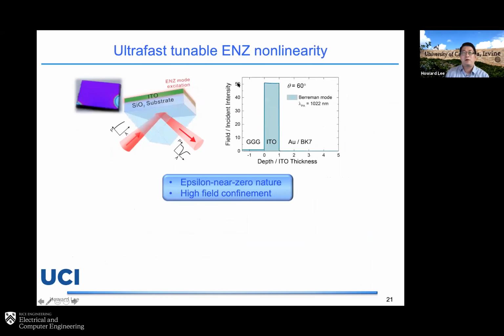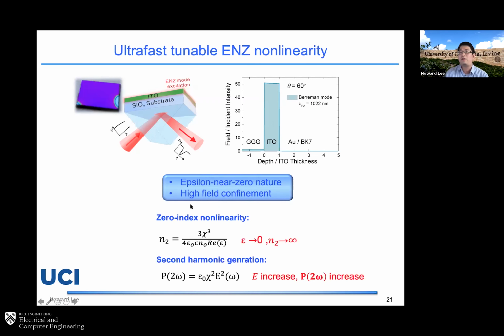But just to take a look at why the ENZ material may have a high nonlinearity. There are a couple of explanations people have been discussing recently. For example, one is the ENZ mode. You can have a really slow light dispersion of the ENZ mode. At the same time, you may have a really strong field confinement, so you can enhance the electric field to enhance the nonlinearity. And if you take a simple approximation, let's say the Kerr nonlinearity, the n2 is basically inversely proportional to epsilon. If your epsilon is close to zero, then your effective n2 can be enhanced quite significantly.